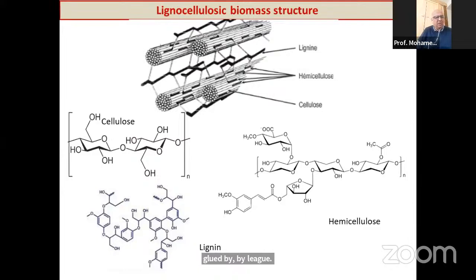There are some Chinese groups who work very actively on the mechanism of carbonization and the transformation of these molecules and polymers into sp2 carbon materials. This is outside the scope of our work, although we started to think about using TGA, thermal gravimetric analysis, coupled to infrared and mass spectrometry to study our agro waste and see how it gets carbonized during the pyrolysis process. So we simulate the pyrolysis conditions with the TGA setup. But for the moment it's in progress, and I will not mention this.